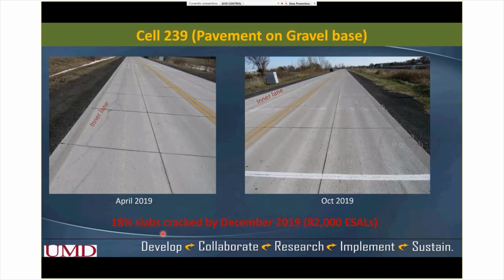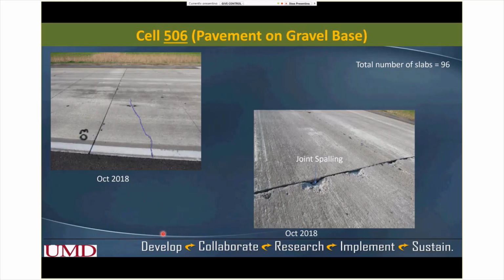Cell 506, which was the only cell which didn't have fiber, we had around 96 slabs in this cell. All are 6 feet by 6 feet, and then we saw only one crack in 2018, but we have seen some spalling on the transverse joints, as many as, I think, 15 locations we found out to have spalling like this.